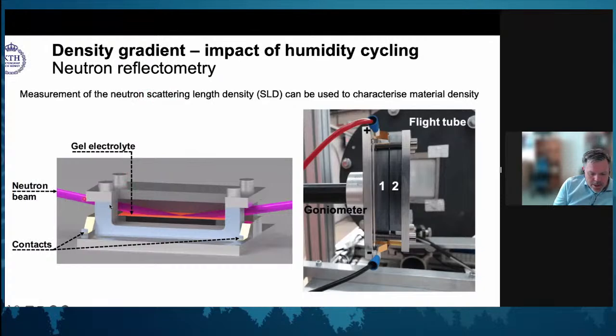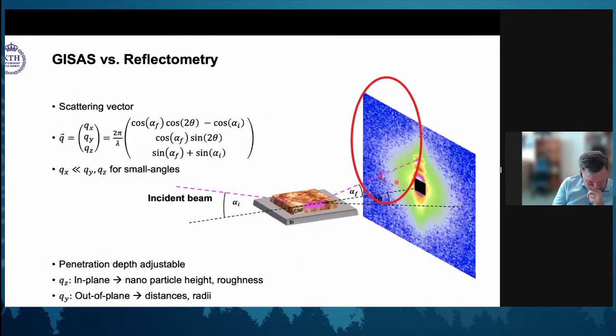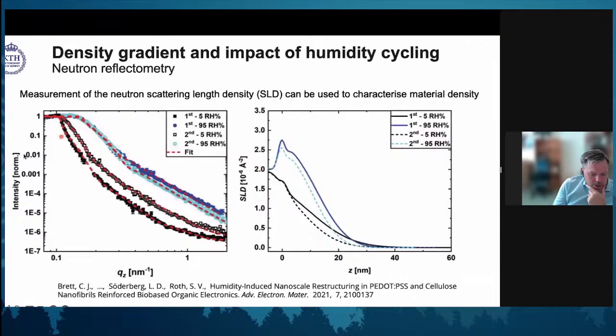So in this case, we have a neutron beam, and our electrolyte, or actually it's a film, mounted into the neutron beam. We are looking at what happens only out of plane here, so the thickness direction, and what we get then is an intensity curve throughout the thickness of the sheet.